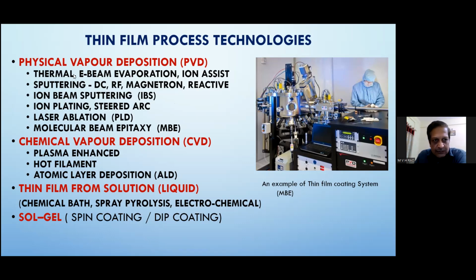If you go through it historically, the initial methods were thermal. Then to vaporize the high melting point materials, there is the electron beam evaporation. And then the sputtering method, which is DC discharge. Basically, you have two plates, cathode and anode. You make one of them the target, which is the cathode. Then you put in an ionized plasma and accelerate, give energy to the ions, argon. Argon is used because it's a very inert material. So argon ions bombard the target and knock off the material from the surface. Once it comes out in the form of a vapor, it gets deposited on the substrate.